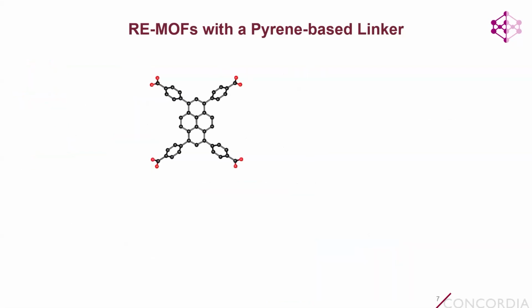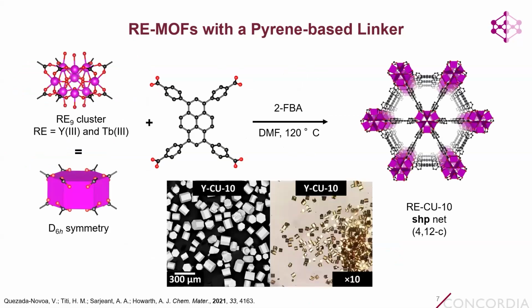And so to start this, Victor first synthesized this tetratopic pyrene-based linker. He then reacted it with a rare earth precursor using 2-fluorobenzoic acid as the modulator in DMF at 120 degrees Celsius. And he obtained these nice and beautiful single crystals that you can see here. And so we were able to determine the structure of this MOF using single crystal X-ray diffraction, actually with the help of Amy Sarjeant, who used to be a crystallographer at Northwestern, so people maybe know her. And so you can see these beautiful single crystals.